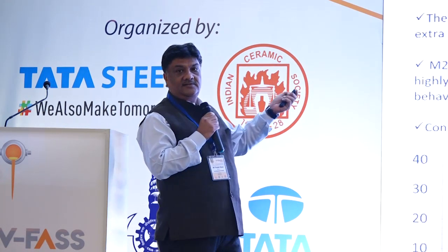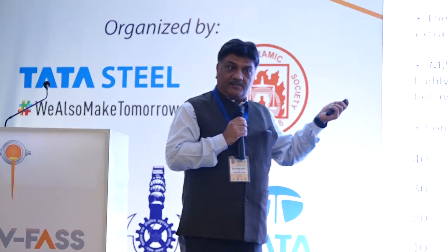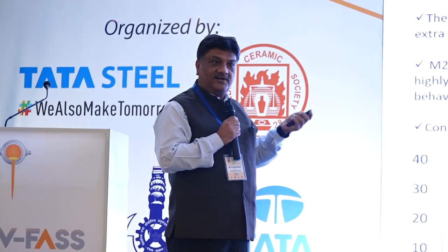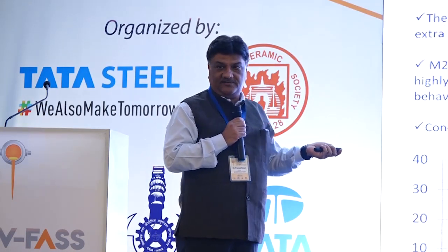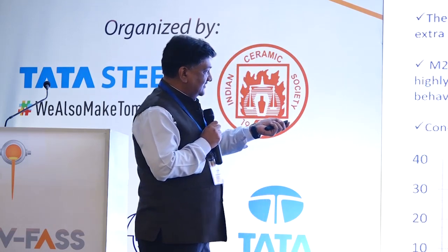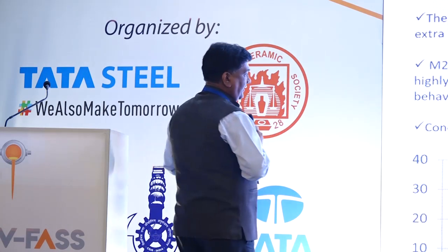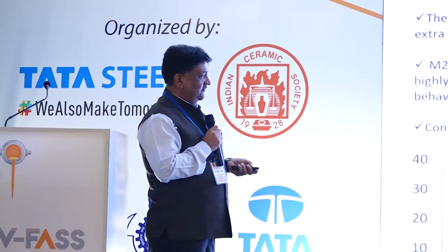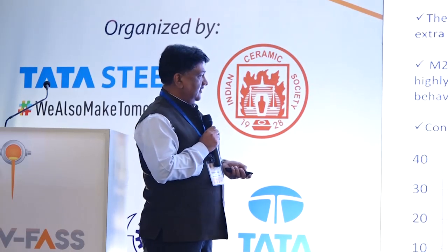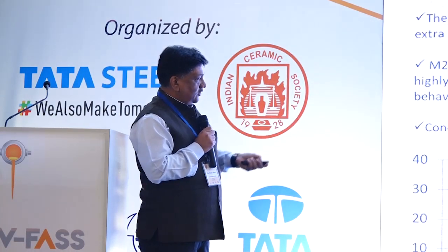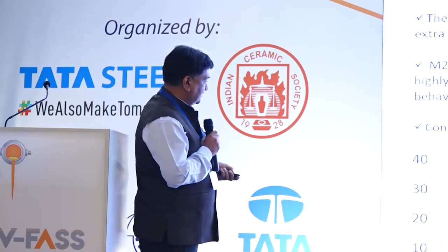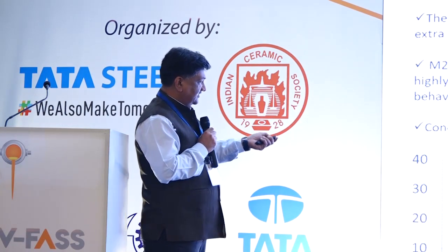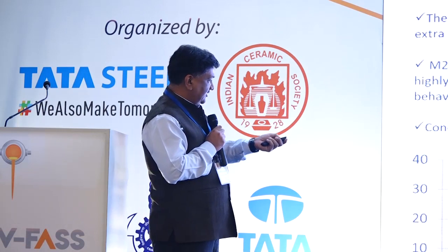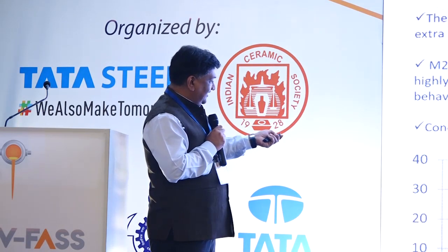We did that, but the amazing and surprising result was observed that it was benefiting the concrete behavior. You can see the rapid chloride penetration behavior at 25% fly ash replacement. It was around 3,000 coulombs, whereas in the control mix it was 4,000.